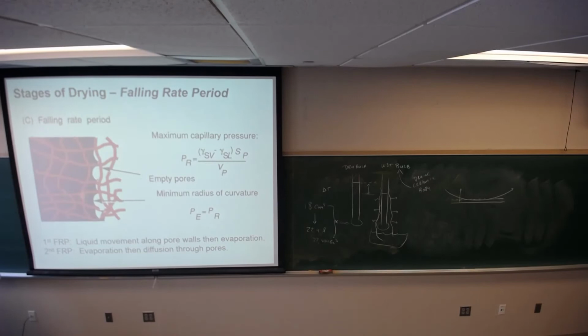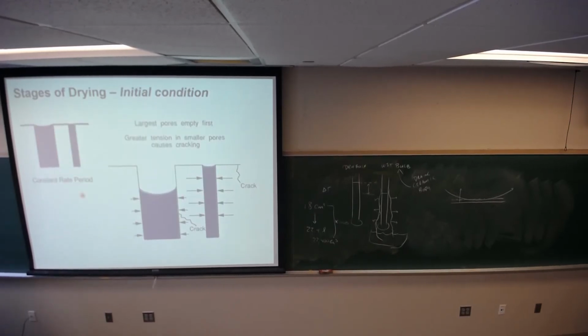We don't have direct data, we have anecdotal data, meaning that we see that the strength of systems containing higher levels of salt after drying are typically greater than the strength of systems which do not have that salt. Okay? It is an argument for the use of tap water in ceramic processing, and it certainly is a good argument for traditional ceramics. It's not such a good argument where you have advanced ceramics that are sensitive to small changes in chemistry. Okay? George then predicts that you will get cracking based on stresses in the system, okay?